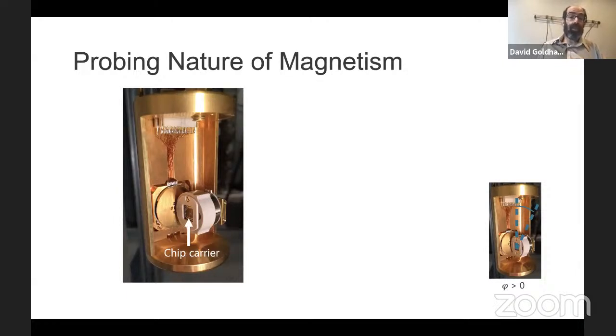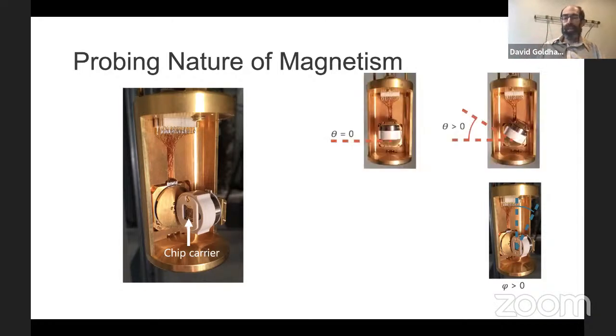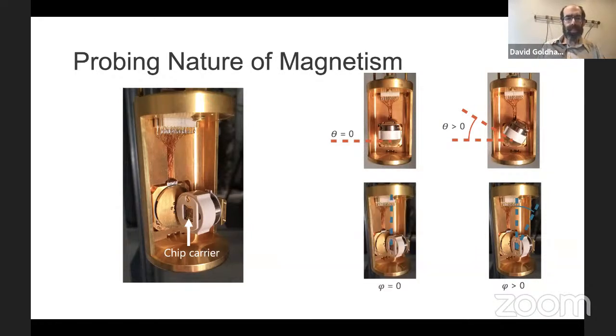I said it's almost certainly an orbital magnet, but to understand in more detail, we applied magnetic fields in different directions, and specifically tilted relative to the sample. So this is a rotator where we can reorient the sample at low temperature and in 2 different axes, so that we can change the out-of-plane field and also the in-plane field, and the direction of the in-plane field. And this is something we designed together with a company, AttoCube.